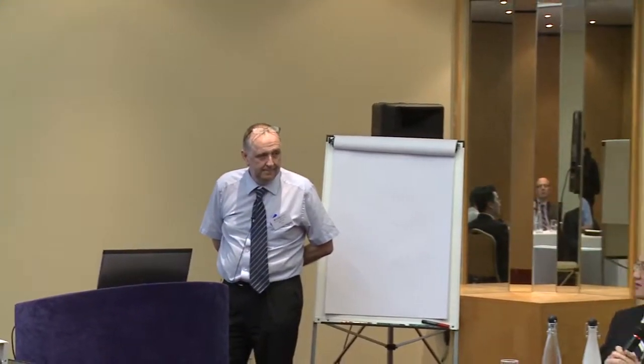Yeah, thanks. I think it's an interesting point about the silver, because with Wayne's talk there, that kind of goes the other way. I think one of the things that's interesting as well is perhaps in the early 2000s there was still quite a lot of mixed technologies. So that's a very good point. That is on my presentation: do not have any lead on your component. That is a glaring omission on my behalf. If you have any lead, you do form a low melting point phase, I think about 183 centigrade, and your assembly will well and truly fall apart. So now we're into more complete lead-free systems, where the risk of lead contamination is a lot lower. Then perhaps that's why there's maybe more uptake for this alloy. One of the reasons, not the reason, just one of them.